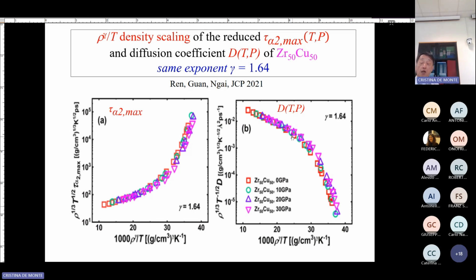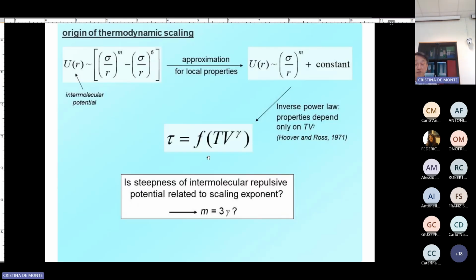This is the long-term diffusion, and this is the Fickian diffusion of the atoms here. So they all have the same gamma, same gamma 1.64. So very general. I won't go into that detail, but just mention there is a basic theory behind that to tell you why the relaxation time depends on TV gamma.